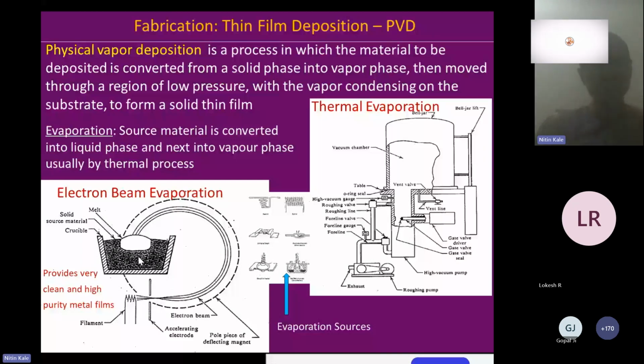And because of the phase diagram for the material, the phase changes from solid to gaseous or to vapor phase directly. And the gold vapor is going to go and sit on the silicon wafer. And it's going to deposit there as a gold film. Whatever you did thermally, you can also do it with electron beams. You can do a local evaporation and you can still deposit the material.